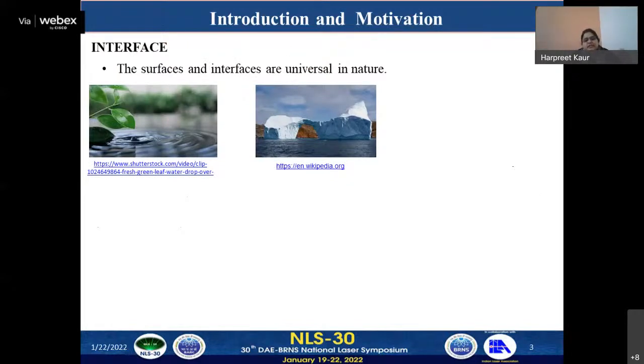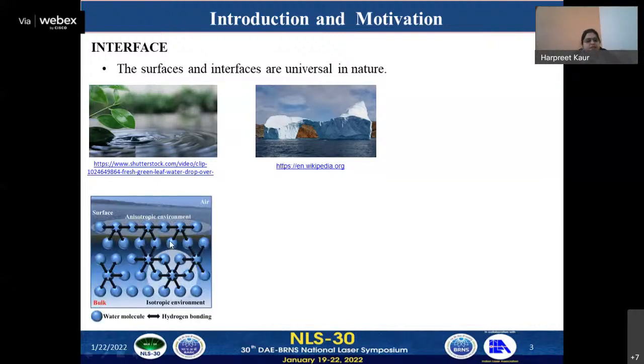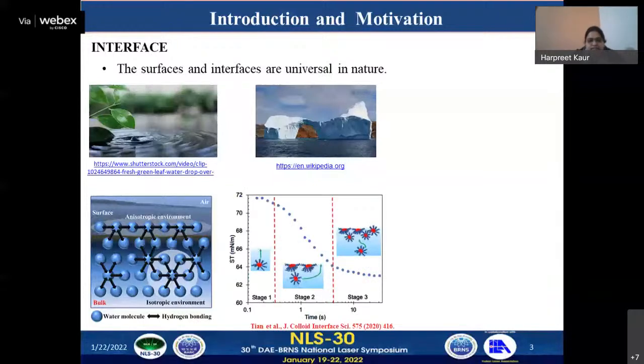Surfaces and interfaces exist everywhere in nature. Here you can see examples of natural interfaces: the air-water interface, the air-solid interface, and the solid-liquid interface. The molecular arrangement at the interface is quite unique, and the interfacial structure and properties are quite different. For example, the difference between the force experienced by a water molecule at the interface and in the bulk gives rise to the surface tension of the liquid, and this surface tension depends on the interaction of the molecules. For example, Tim et al. have shown that there is a decrease in the surface tension when there is an increase in the interaction between the nanoparticles